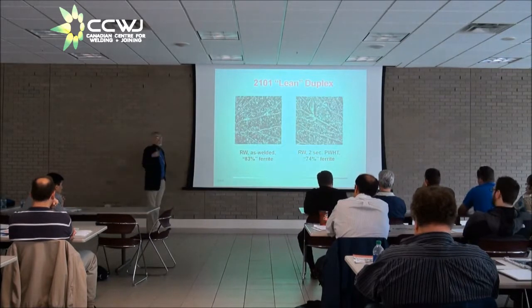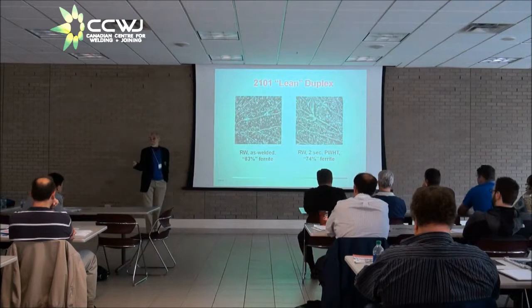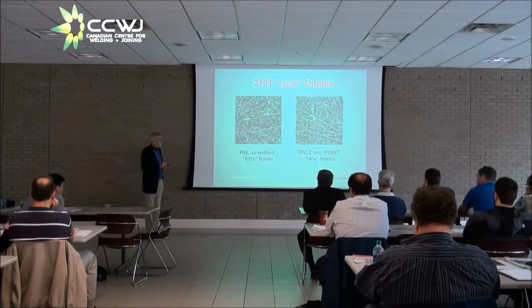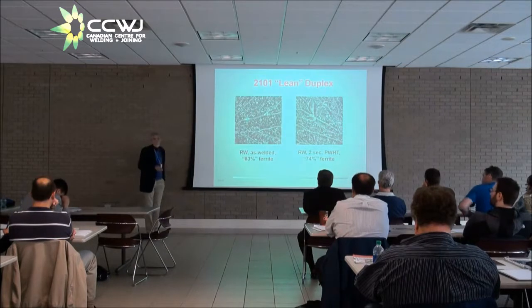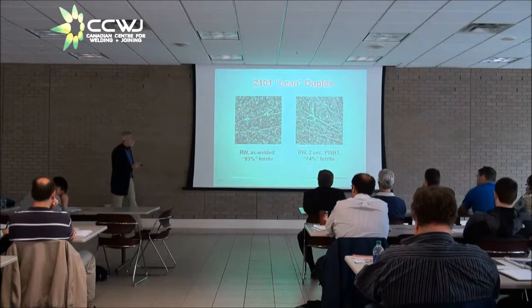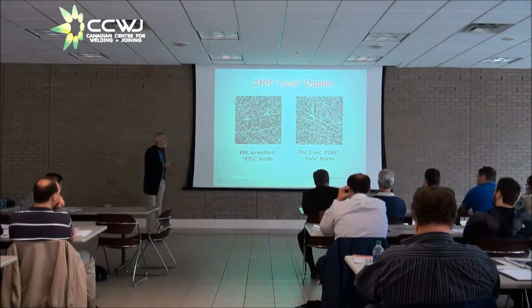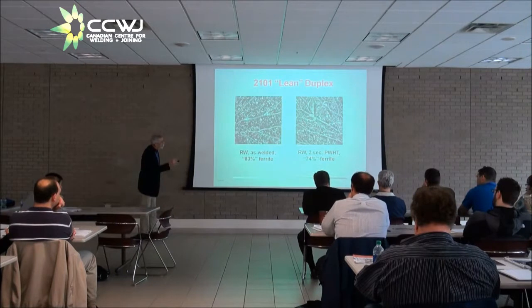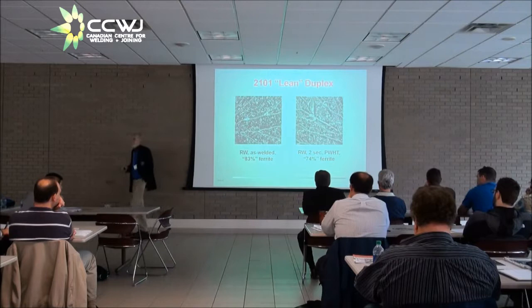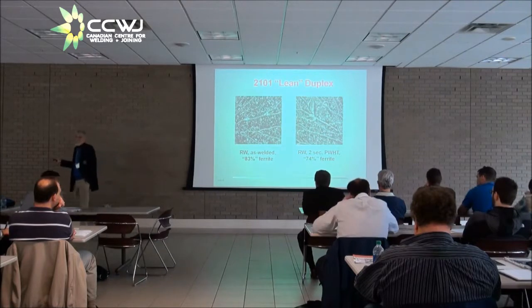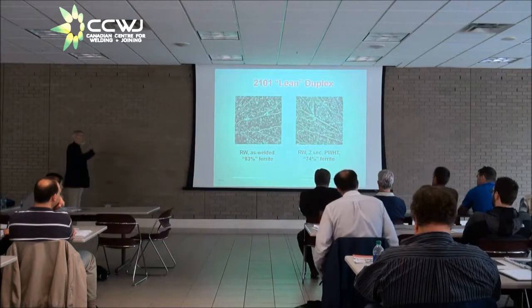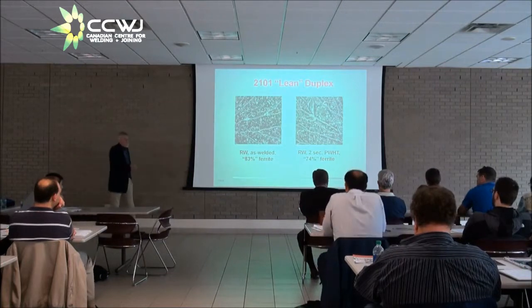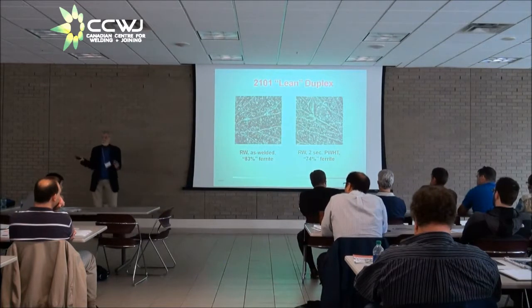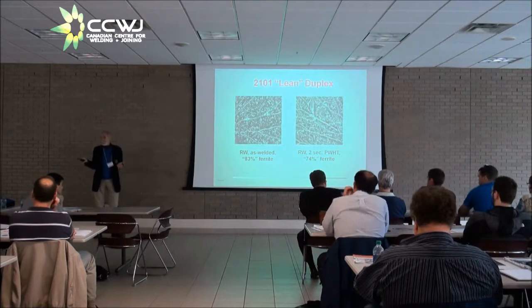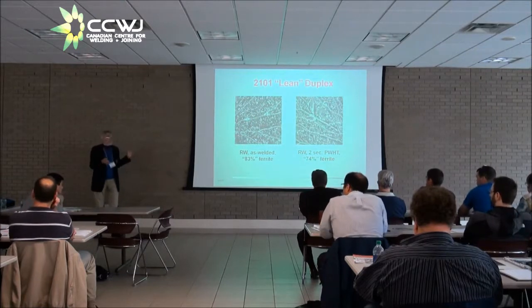But in a resistance welding machine, after the resistance welding cycle itself is done, you can pulse the resistance welder a second time. A 2-second pulse of energy drops the ferrite content from 83% to 74%. What it particularly does, and I'm not sure you can see it as well here as you might in a paper version, is greatly reduce the amount of chromium nitrides in the dark areas. They're discontinuous. You can live with it. You can get useful mechanical properties out of a resistance weld that is post-weld heated with this little 2-second post-weld heat treatment. You can get useful mechanical properties and useful corrosion resistance. So you can make things like dimple jacket heat exchangers by resistance welding.